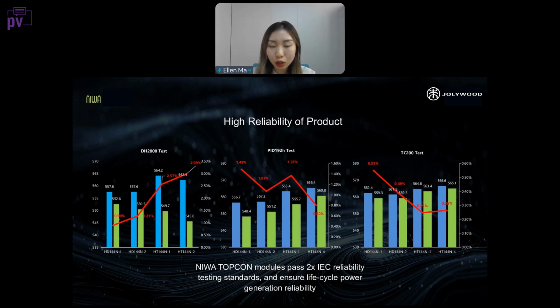And we have the TC200 test, which is the thermal cycle test, standing for high temperature operation. We can see that under this test, the degradation rate is around 0.5% to 0.25%, which means it's almost like no degradation. So we can conclude that all of the newer products have passed 2 times the IEC standard testing to ensure reliability for the end customers.